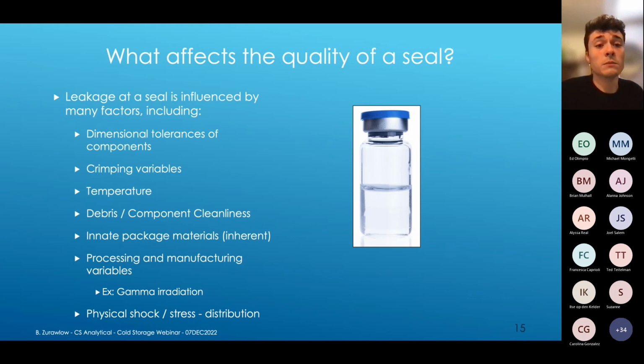So what affects the quality of a seal? Leakage at a seal can be influenced by many factors, including dimensional tolerances of components, how those components physically fit together to create that seal, how those crimps are applied, how those components are mated together through the crimping process. Temperature, as we'll see, is certainly something that can impact the quality of a seal. Debris, any debris on that component that could interfere with that seal, create a channel, of course, can have a problem or an impact on quality. Innate package materials could impact the quality of a seal. And then, of course, other processing and manufacturing variables. For example, gamma irradiation can have an impact on the way that that elastomer behaves, which in turn can impact the quality of a seal. And so as we go through and we think about building a product package system that's going to be suitable for its intended use, we need to consider to a large extent these attributes and how they come into play.